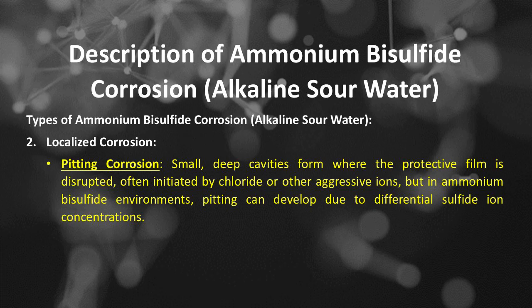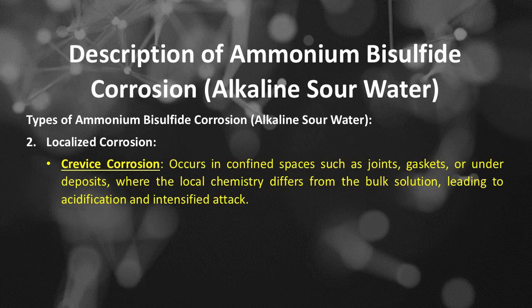Pitting corrosion occurrence is small, deep cavities form where the protective film is disrupted, often initiated by chloride or other aggressive ions, but in ammonium bisulfide environments, pitting can develop due to differential sulfide ion concentrations. Crevice corrosion occurs in confined spaces such as joints, gaskets, or under deposits, where the local chemistry differs from the bulk solution, leading to acidification and intensified attack.